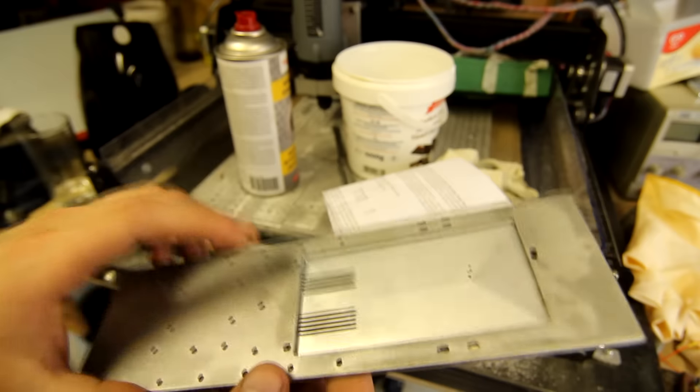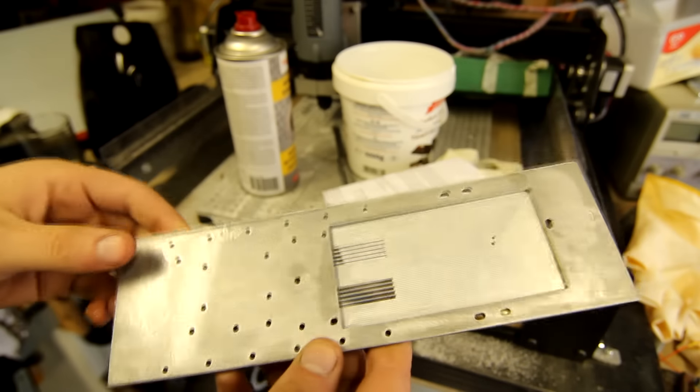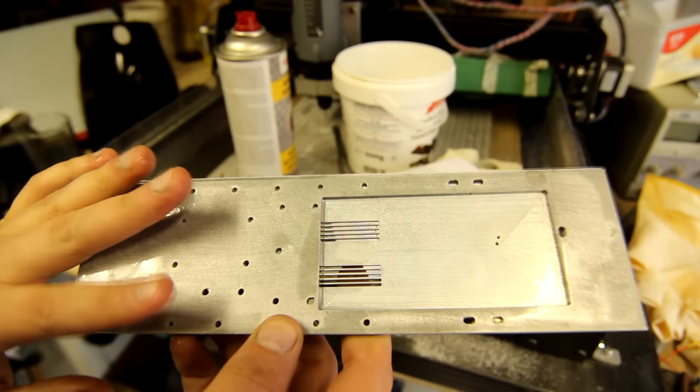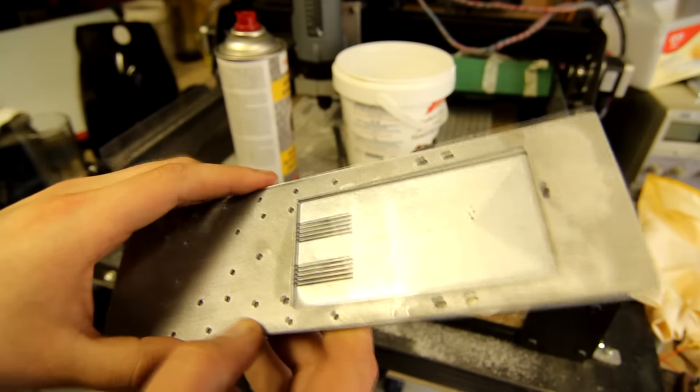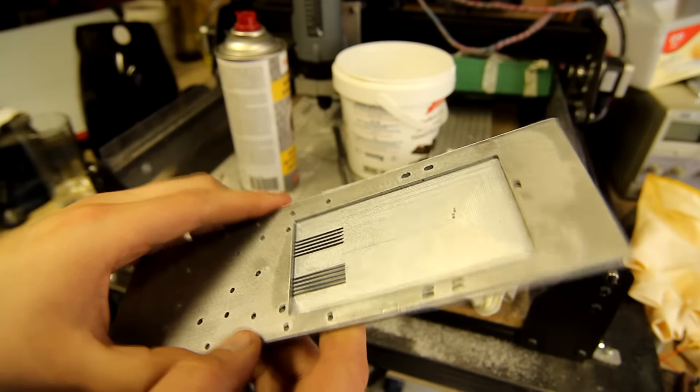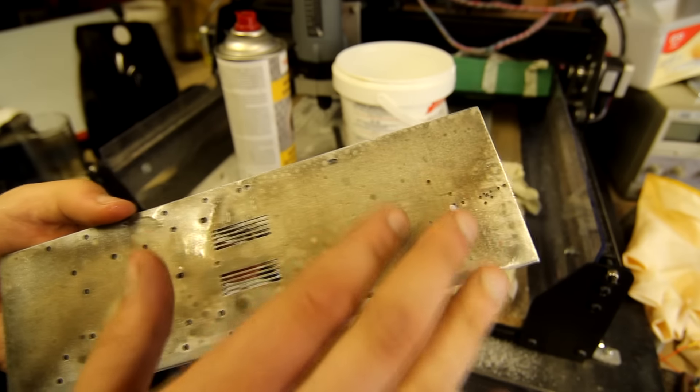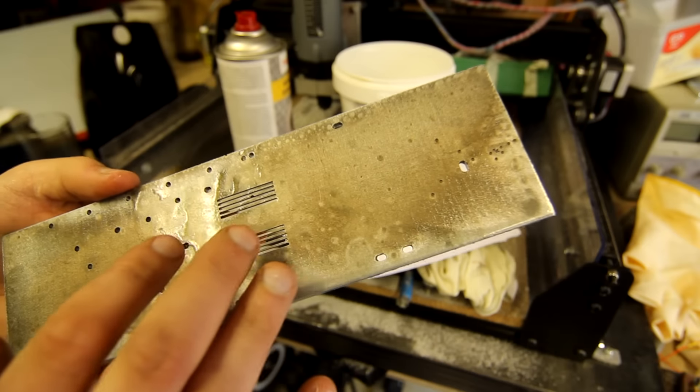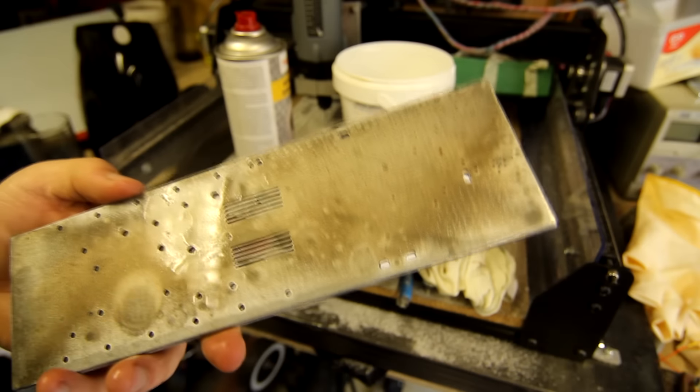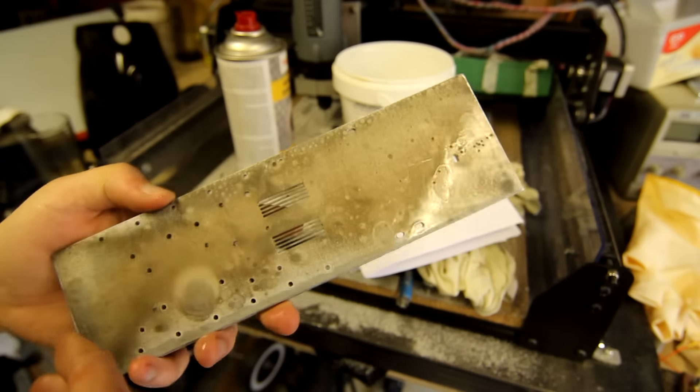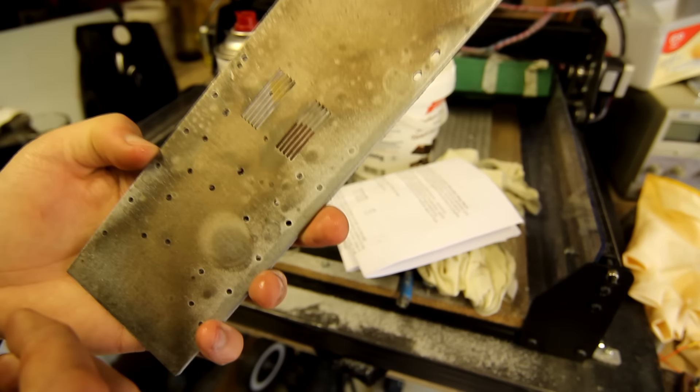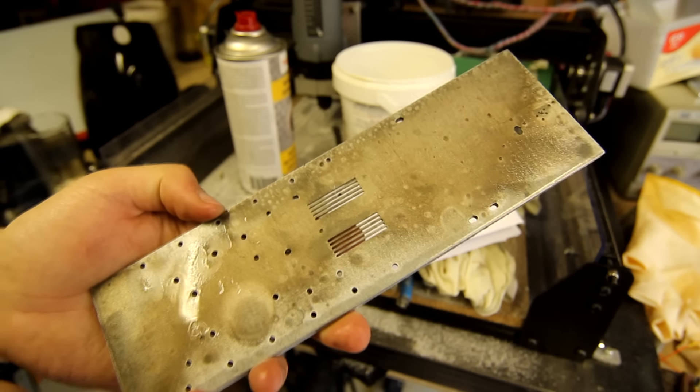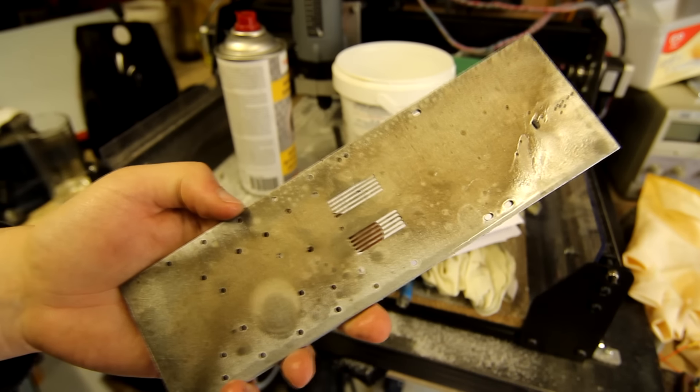And then lastly, the color didn't actually get in. And that's probably due to the anodization being way too shallow. Although I do fear that if I would have gone on for longer, the pits would have grown into actual holes. So let's just not try doing that for longer. So yeah, I'm going to experiment much more. But hope you liked this very first time trying to anodize a piece of aluminum, which has miserably failed.